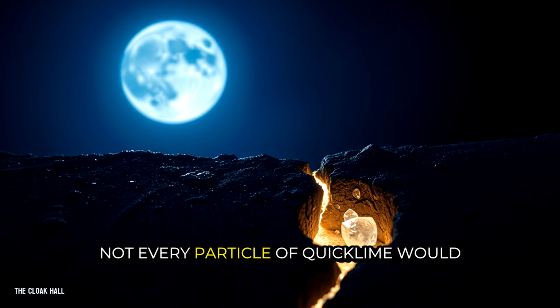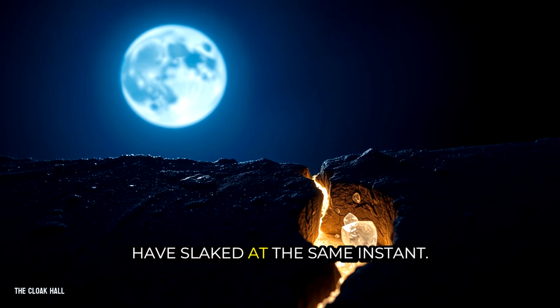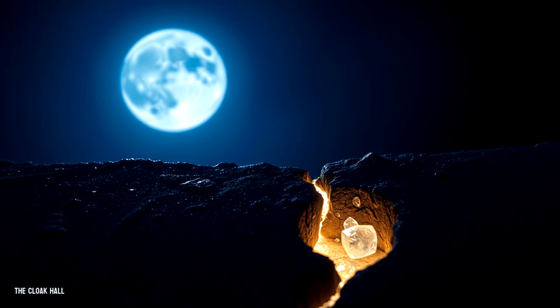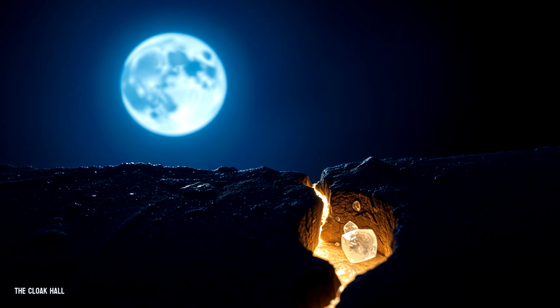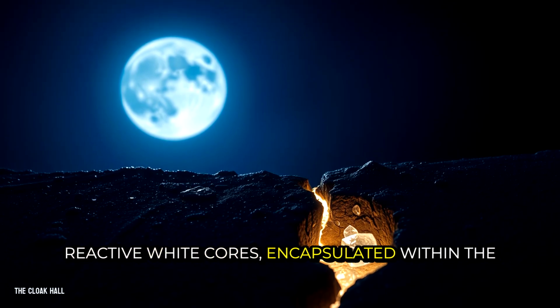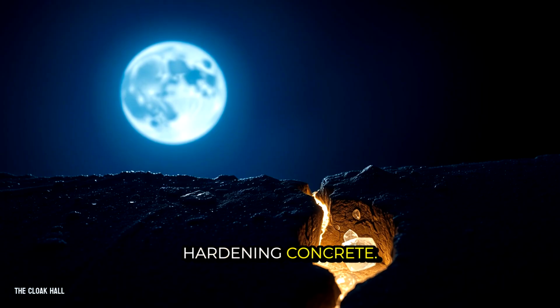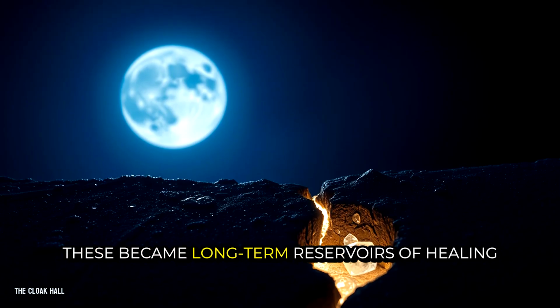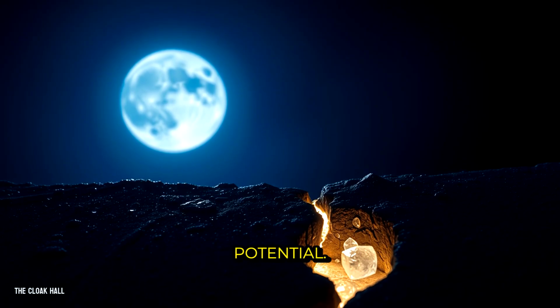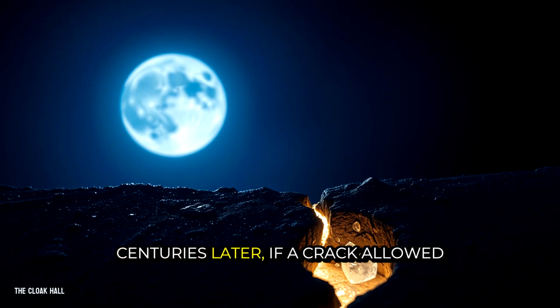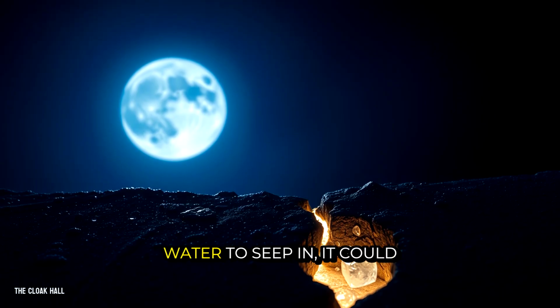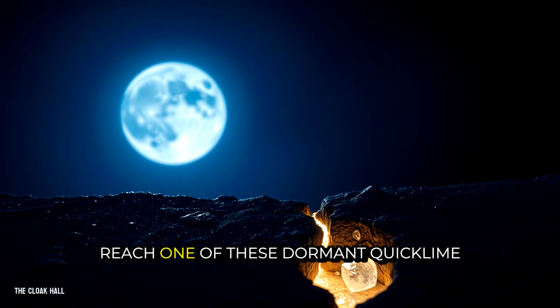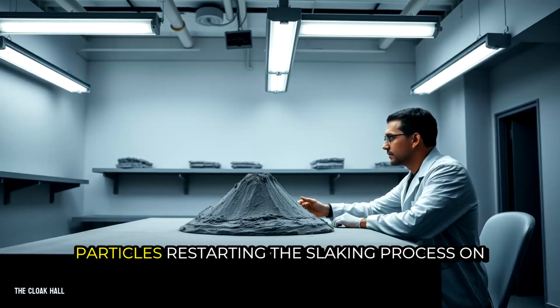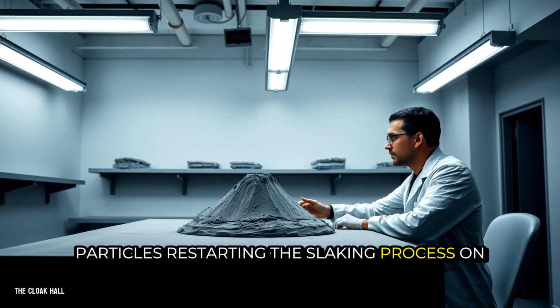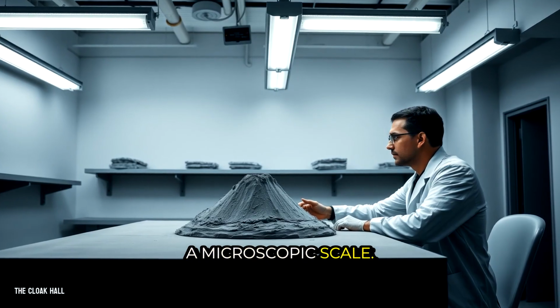Not every particle of quicklime would have slaked at the same instant. Some would have remained as tiny, reactive white cores, encapsulated within the hardening concrete. These became long-term reservoirs of healing potential. Centuries later, if a crack allowed water to seep in, it could reach one of these dormant quicklime particles, restarting the slaking process on a microscopic scale.